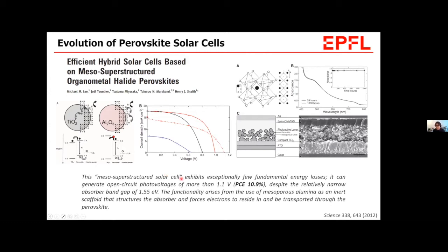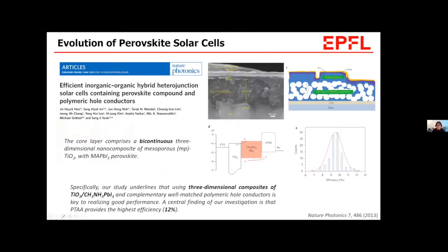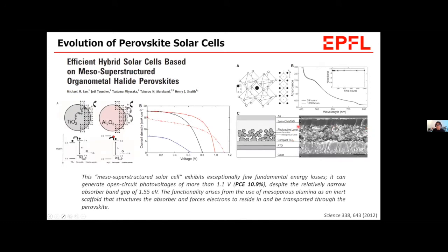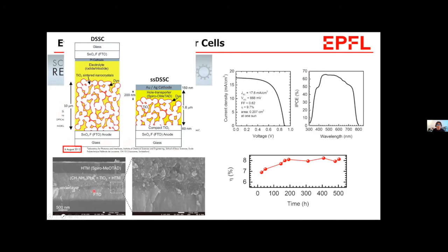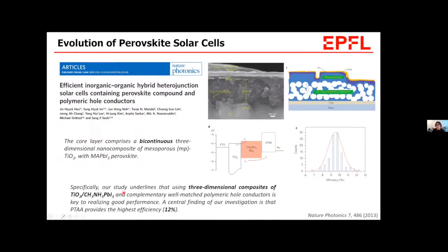Then people got some insight that maybe we could increase the thickness of the perovskite more. So here we see this bilayer-like layer, partly, as you can see in this figure. In previous work, you may remember that the thickness of the perovskite layer itself was not exceeding. They are all overlapped like this. Here as well, they didn't have an additional perovskite layer, but here they did. They call this bi-continuous nanocomposite.